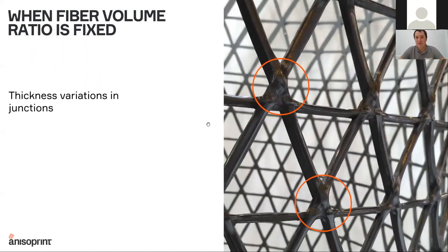That's the example. What could happen if the plastic and fiber volume fractions are fixed? If it's just the pre-preg placement, where you do not have a separate channel, a separate stream of plastic that is controlled independently from the fiber, you will have such bumps in the intersection, an increase of thickness, which first of all decreases the properties of the material a lot due to irregularity and fiber waviness, and makes it very hard to do complex lattice designs because of these variations and imperfections in the intersections.